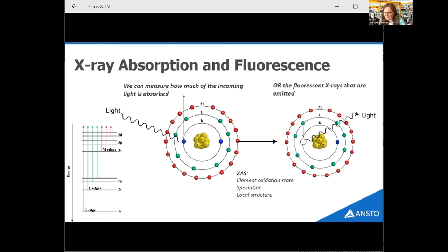In the first way, for absorption, we simply measure the intensity of the X-ray beam before and after the sample to see how much has been absorbed. In the second case, to measure fluorescence, we set up a detector that measures the photons that are emitted from the sample, and it also measures what their energy is. So this involves two beam lines. So it's the XAS beam line, where we can do both, and the XFM beam line, which has mapping capability.